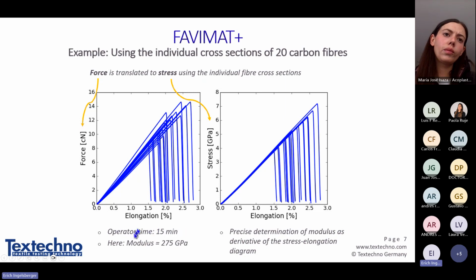Important is the operator time here - for, I believe it was 20 fibers, it is about 15 minutes. So after 15 minutes, you have your results for 20 carbon fibers. Now compare this to the necessity of measuring the diameter fiber by fiber and then gluing this onto paper tabs and so on - it's much faster.